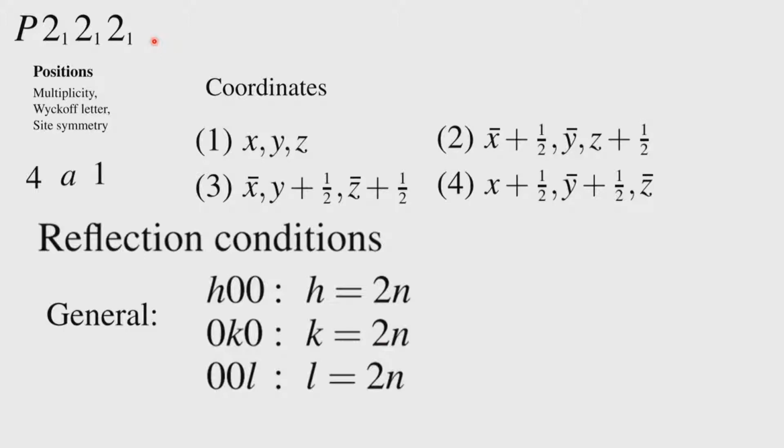So, this is an advantage because in these kinds of systems the symmetry elements do not intersect with each other, and this is a non-centrosymmetric system, and in the non-centrosymmetric system there is no question of having a center of symmetry and also its association with the origin. So, the origin has no special significance in this space group except that it has to have the 3 two-fold axes perpendicular to each other removed by 1/4 from this origin in each direction. So, that will generate these systematic absences. So, P212121 again is a space group we can uniquely determine.